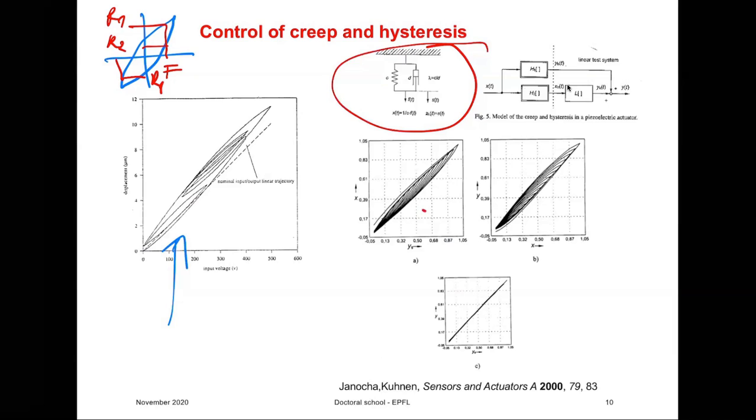Basically, if you have a signal that is like this, you give feedback that is opposite of that, and you can get a straight line in your response. You can completely remove this creep and hysteresis. Now, very often, this equivalent circuit actually doesn't describe the material physically accurately. And one way to do that is to use this Rayleigh model that I told you. You can add additional terms, and this works very nicely to handle this situation. So one paper which you can check if you're interested in this is